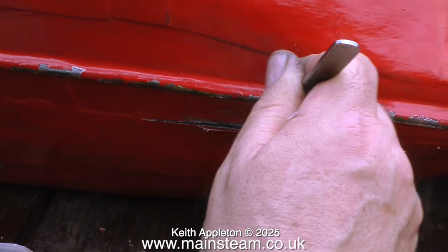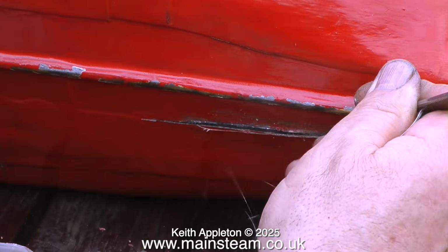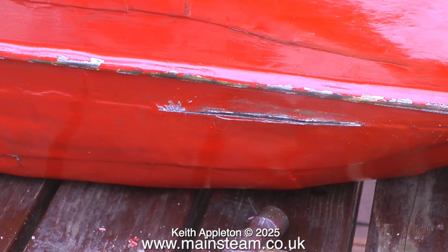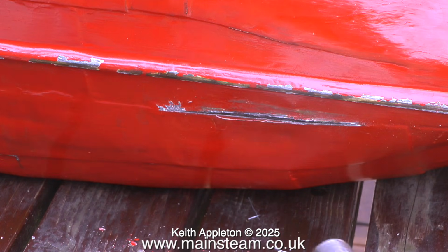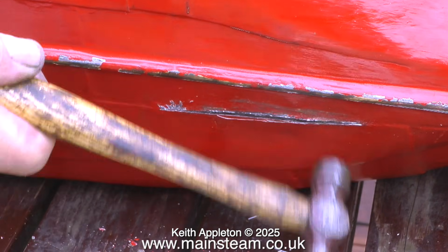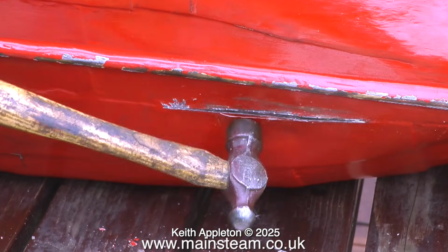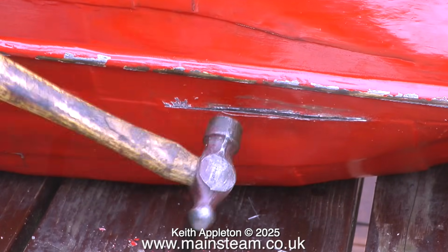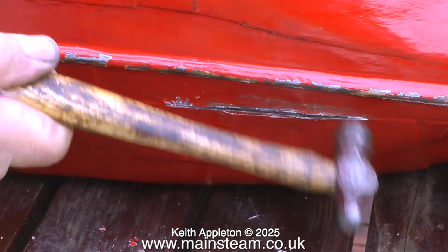It looks a little bit like impact damage, as though part of the hull got dinted and that separated some of the plates. I'm trying to tap them back with a hammer, very gently of course. And the hammer's not really doing much, it's closed the gap very slightly. But once I fill this gap with JB-Weld and then fill over the top with car body filler, rub it down, etc., and paint it, it will be fine.